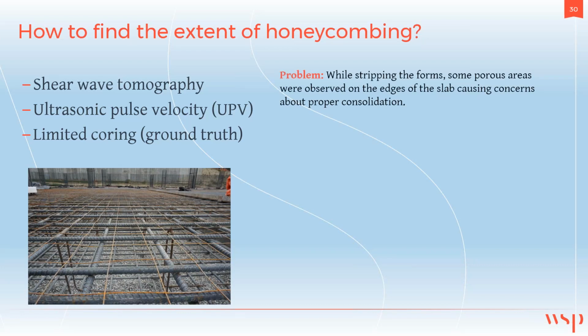This is a water reservoir, and these are the rebars for a 3-foot thick slab. As they were pouring concrete, one of the vibrators broke. Afterwards, when they stripped the forms, they saw that some porous areas appeared on the edges of the slab, so there were some questions raised whether concrete was properly consolidated or not.